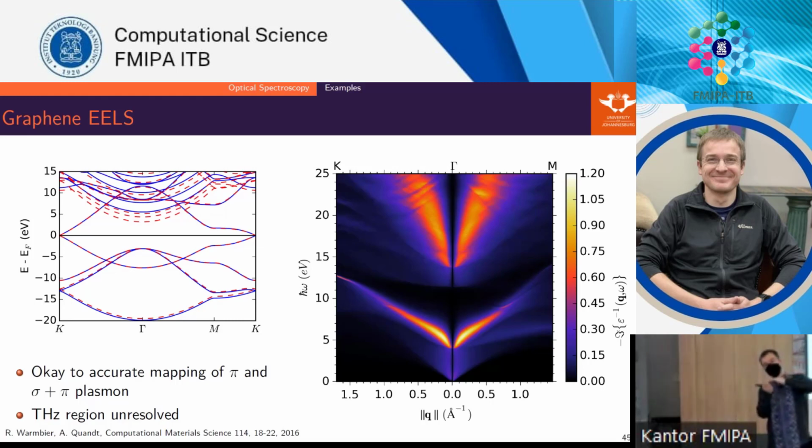And if you start with the 2D electron gas, you immediately get an analytical expression, which always gives you plasma frequencies in the terahertz range. So for us, that is a good indication that this is basically a property of 2D materials, right? And of course, now we have this specific extra thing, the Dirac cone. I do not know whether I would get that with a random 2D material in the end. But the effect requires a 2D electron gas, else you cannot get it.